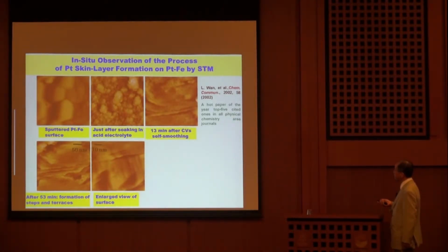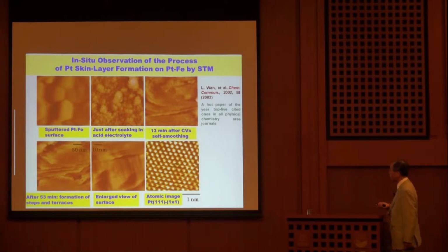But after maintaining the potential constant or cycling, we observe the morphology change, and the surface shows self-smoothing phenomena. After some time, we observe very clear step and terrace structure on the surface. Focusing on the surface structure, it shows the nice spots shown here, which correspond to the platinum 111 1 by 1 structure.